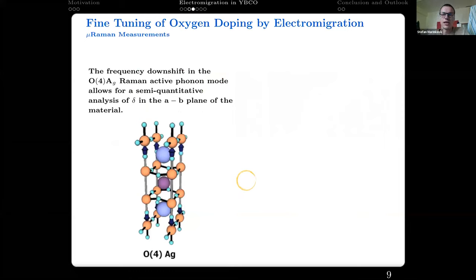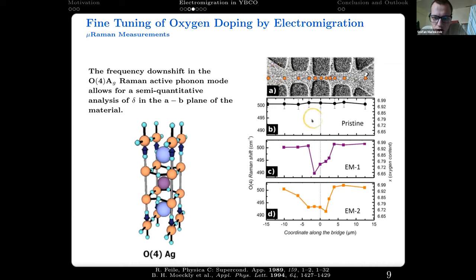We have similarly, like Anna mentioned, used the O4 phonon mode, which is Raman active both in the orthorhombic and the tetragonal material, to get an idea of the oxygen content of our materials. And we have measured after two of the electromigrations I mentioned in the last slide on these points the Raman shift of the O4 phonon mode and compared it to the oxygen content. And we see a clear drop of oxygen content first in the central bridge and then spreading out towards the cathode side, while the oxygen content increases slightly on the anode side, so, giving further proof for change of oxygen concentration as expected.